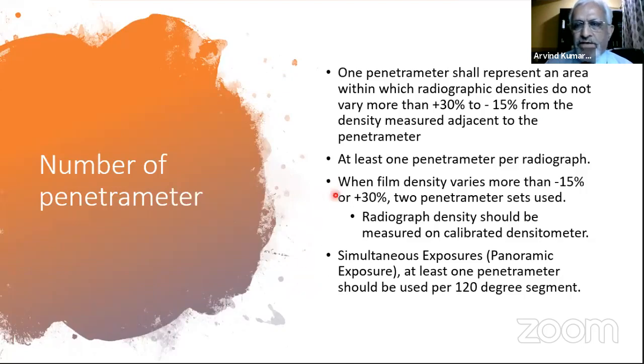Now in the radiograph, there should not be variation in the density. What the code permits is minus 15% and plus 30%. The variation should not be more than that. And with respect to what? With respect to the density that you have achieved in the designated wire that you are required to see. Suppose I am required to see a 0.2 mm wire, then across the wire from the base metal to the weld, I check the density on the weld, and whatever density I get, that density should not vary in the entire film from minus 15 to plus 30%.